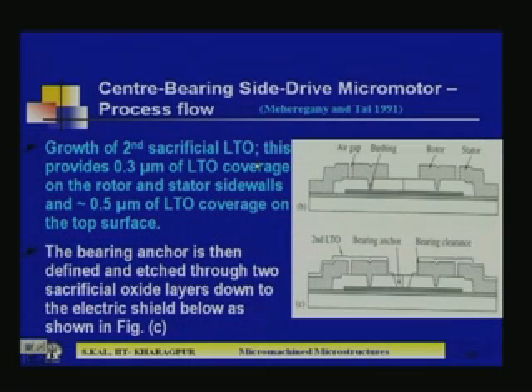Second sacrificial LTO, which is shown there, is here. This provides 0.3 micron of LTO coverage on the rotor and stator sidewalls and 0.5 micron of LTO coverage on the top surface. The bearing anchor is then defined and etched through the 2 sacrificial oxides down to the electric shield below as shown here. So, now the bearing anchor will be defined, means the sacrificial oxide formed by LTO is removed, and you get the total structure here and here.